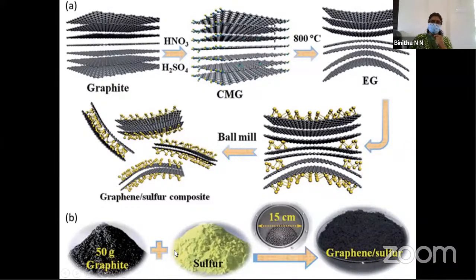For example, graphite can be milled with sulfur to produce graphene sulfur nanocomposite. But initially we need a sulfuric acid, nitric acid treatment and a high temperature treatment in inert condition. The treatment with corrosive acids is not so recommended, but it may not last for hours as in graphene oxide.